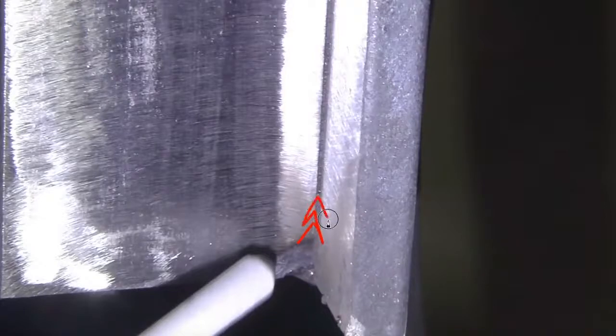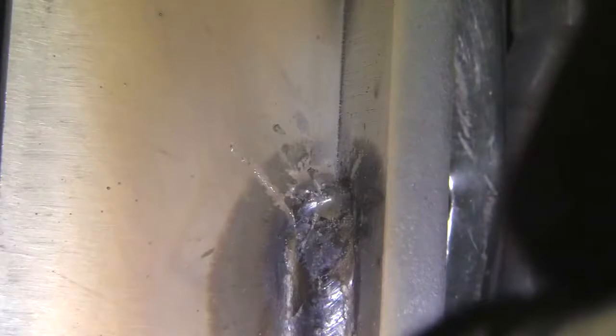Here's a little schematic of the technique used here. It's an upside down V, and coming back on those sidewalls tends to fill in any undercut there might be, and then going forward just keeps your arc on the leading edge of that puddle, keeps you getting penetration into the root. All right, that's one rod down.